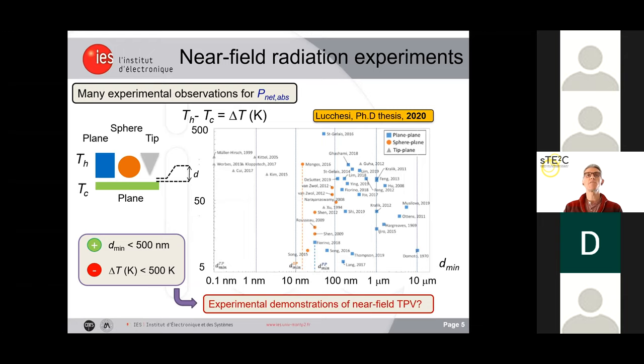There were many, many near field radiation experiments achieved so far. So each point on this graph corresponds to a setup where you have the minimum distance achieved by each setup and the maximum temperature difference between the emitter, the hot plate, and the cold plate. So you see that there are different configurations for the geometry, the plane-plane configuration, the sphere-plane configuration, and the tip-plane configuration. But what is important here to see is that there are many experiments for which the minimum distance was smaller than 500 nanometers. However, the maximum temperature was never above 500 Kelvin.